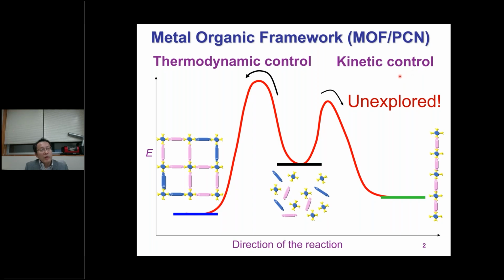Many people know the presence of some kinetic product. However, people didn't try to use this kinetic product, because in the thermodynamic product case you can easily crystallize. Then you can know the crystal structure by single crystal analysis. However, in the kinetic product case, in most cases, you can obtain that only as a crystalline powder. So in this case, it's quite difficult to solve the crystal structure using powder diffraction.